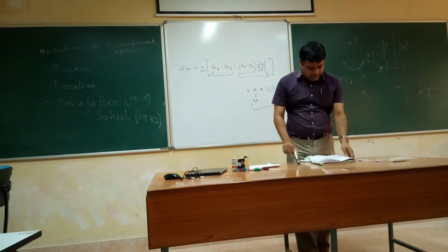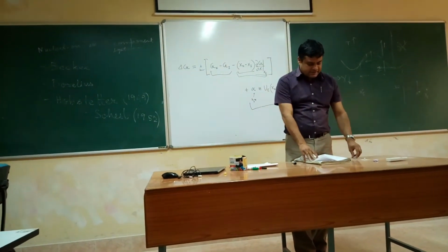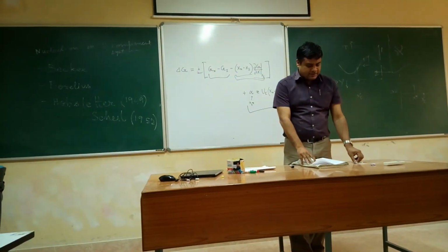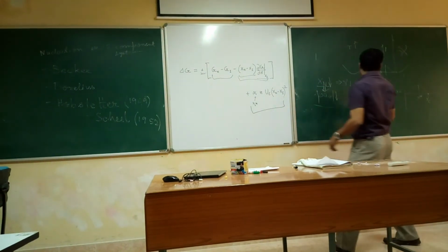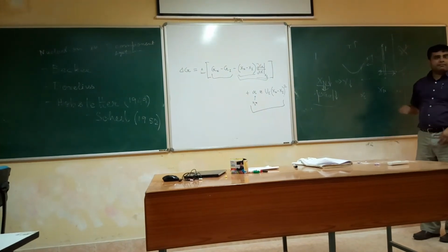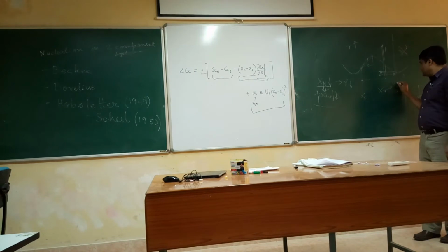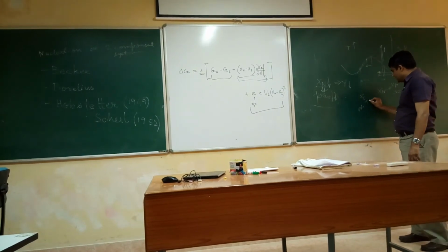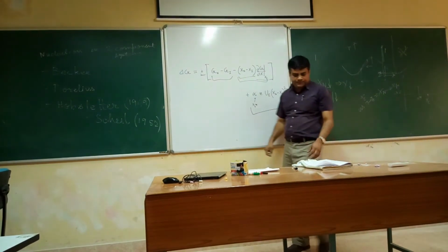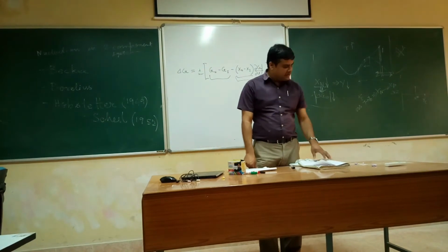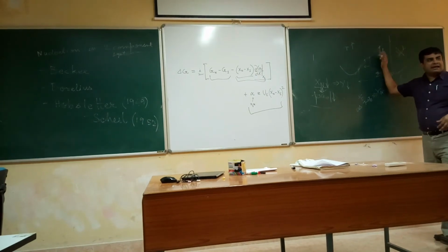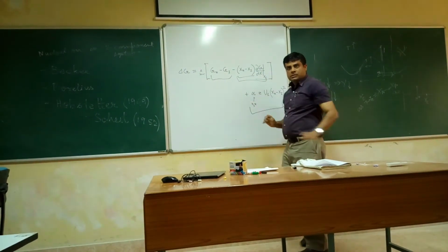It has been seen that as the supersaturation decreases, or the temperature goes close to your transformation temperature, the embryo composition Xn approaches X beta. As T approaches Te, your Xn approaches X beta. And at high supersaturation, the nucleus composition will be somewhere in between X beta and Xc, whichever balances these two terms.